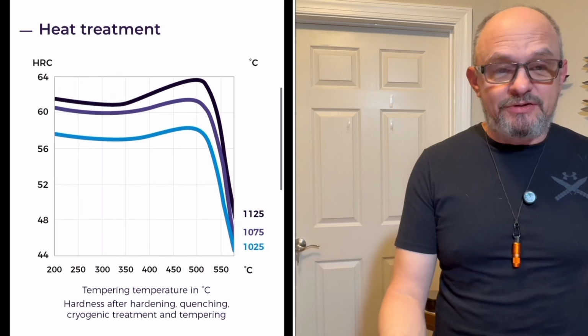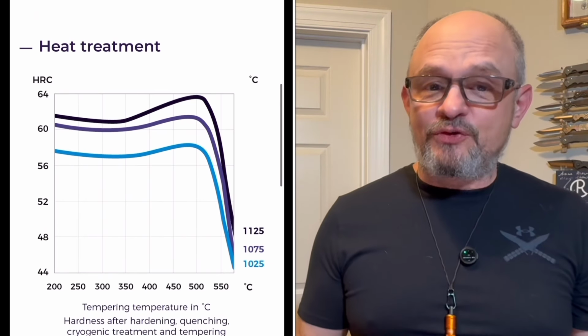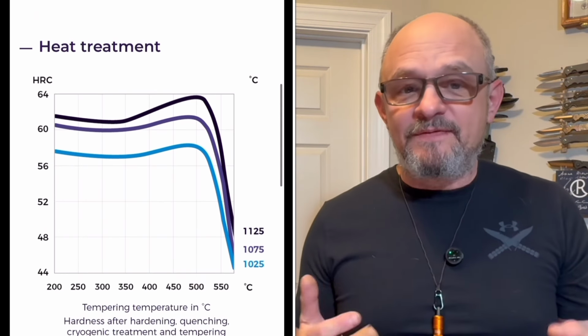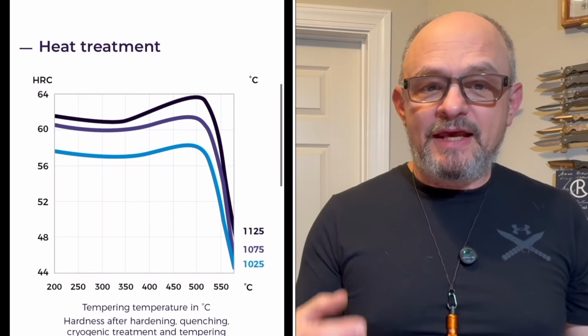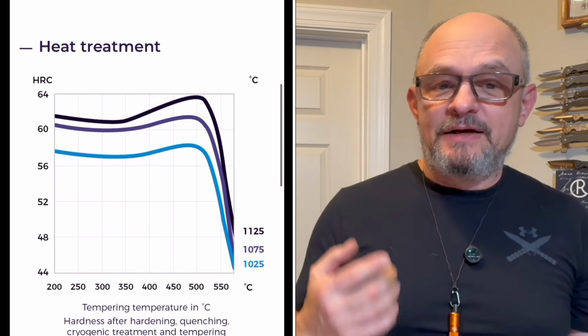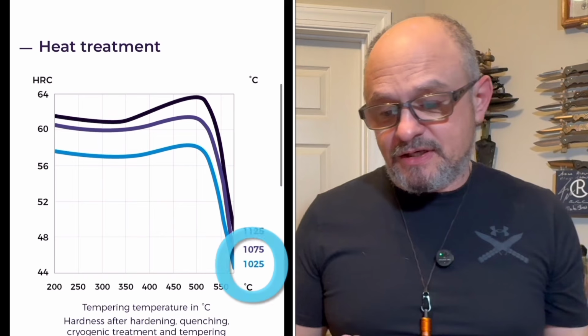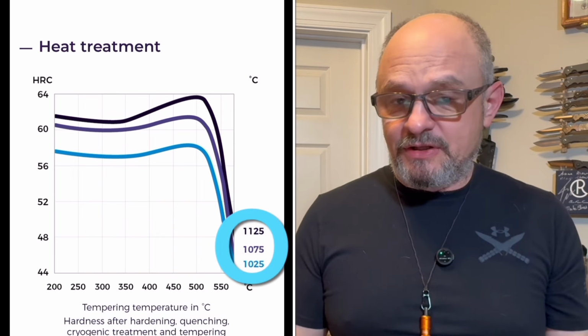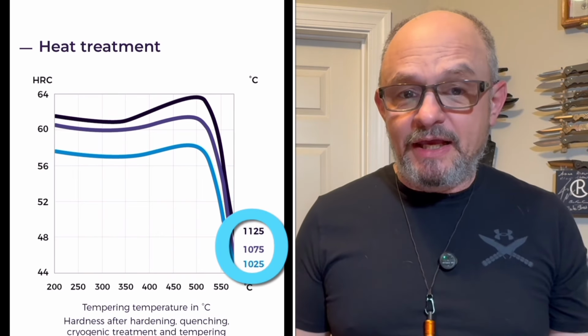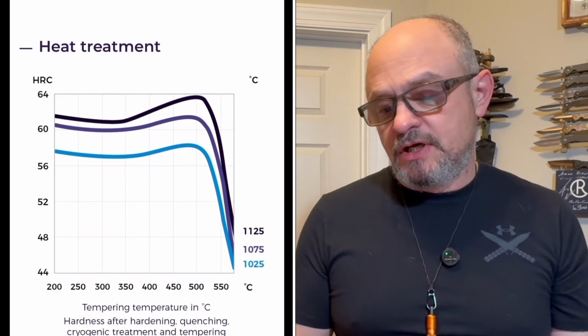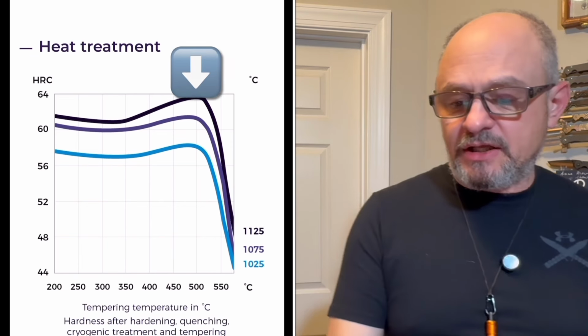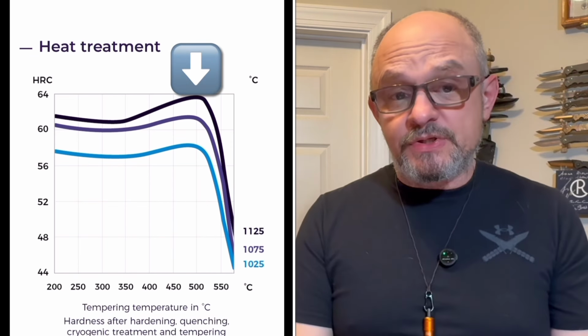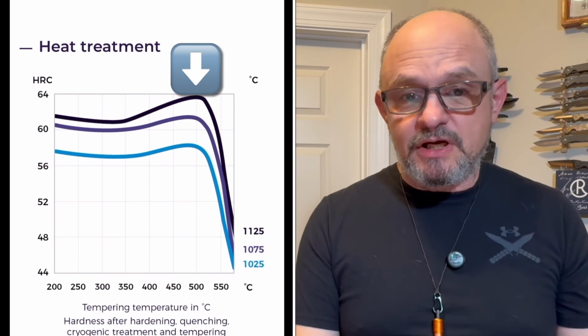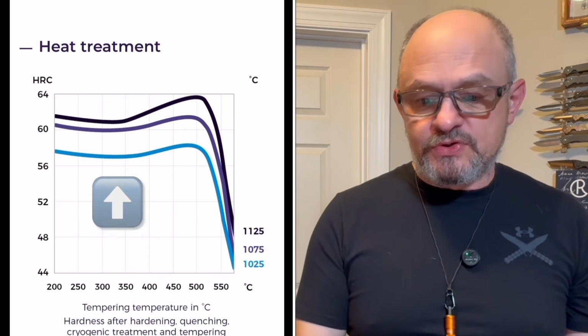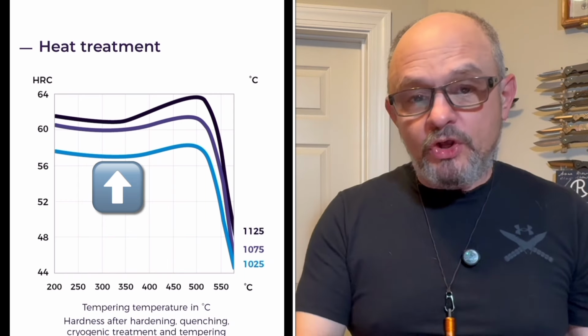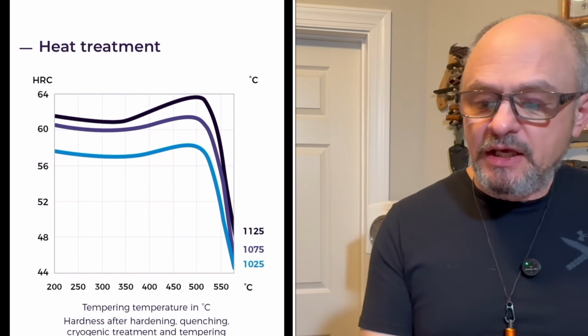Take a look at the heat treatment charts. It's different from other powdered steels in a very important way. It has a very high tempering temperature. It's reasonably high, but not extraordinarily high austenitizing temperature. And they say that black line on the top chart represents the wear resistance optimization for the steel. For corrosion resistance, that's the blue line, or you can balance it out, and that's the line in the middle.